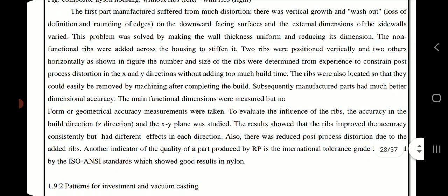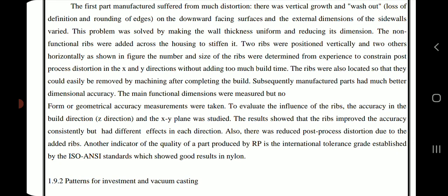The first part manufactured suffered from much distortion. There was vertical growth and washout, loss of definition and rounding of edges on the downward facing surfaces, and the external dimensions of the side walls varied. This problem was solved by making the wall thickness uniform and reducing its dimension. Non-functional ribs were added across the housing to stiffen it. Two ribs were positioned vertically and two others horizontally, as shown in the figure.